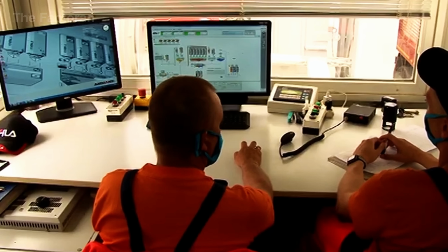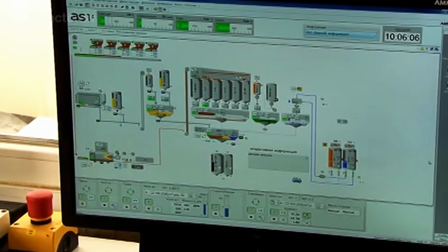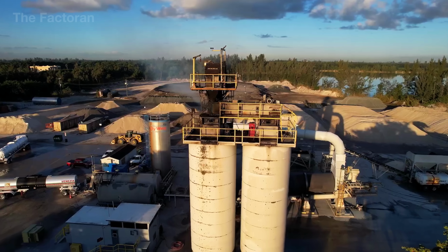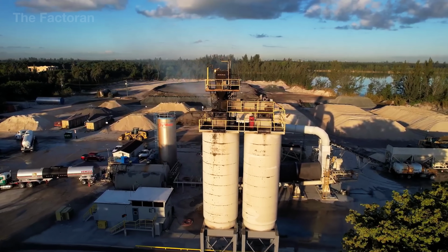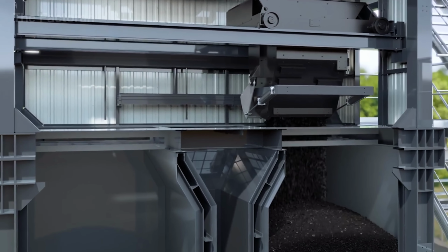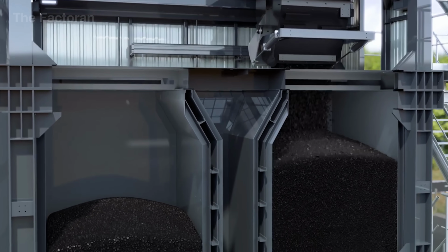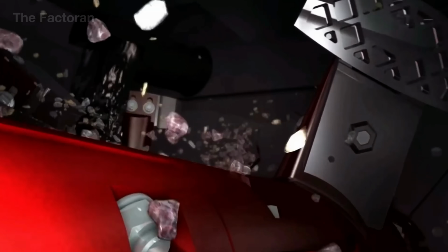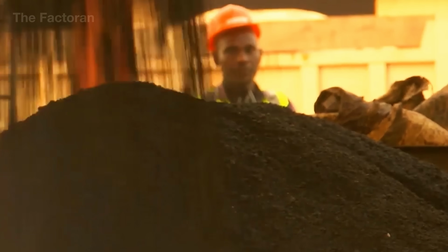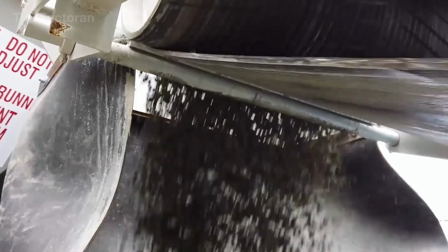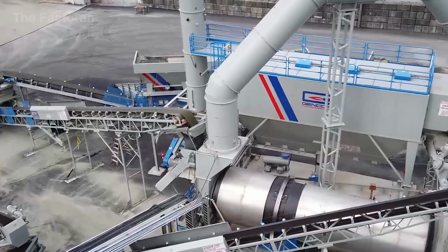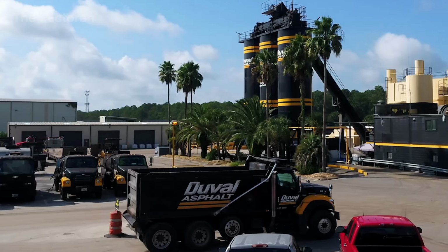When the mixing cycle ends, the hot asphalt mix is discharged into a heated surge hopper located just beneath the mixer. This is a crucial intermediate step. The hopper keeps the temperature steady at about 275 to 300 degrees Fahrenheit, roughly 135 to 150 degrees Celsius, and prevents the asphalt from sticking together. From the hopper, the mix is gradually released into the hot storage bin, where mechanical paddles constantly stir the material so it does not segregate or clump.